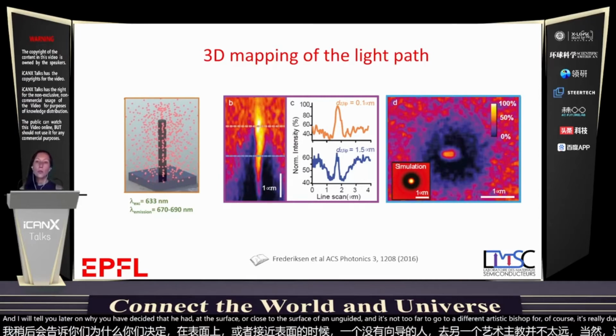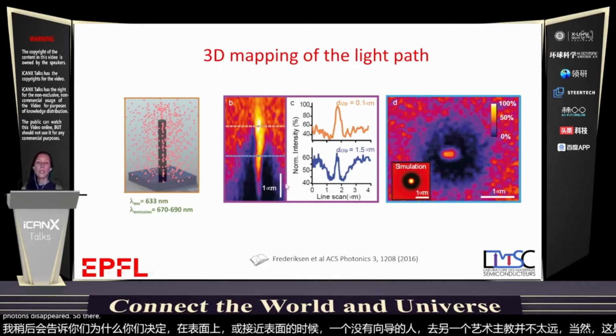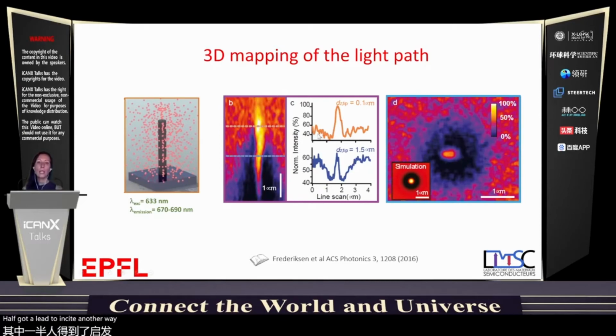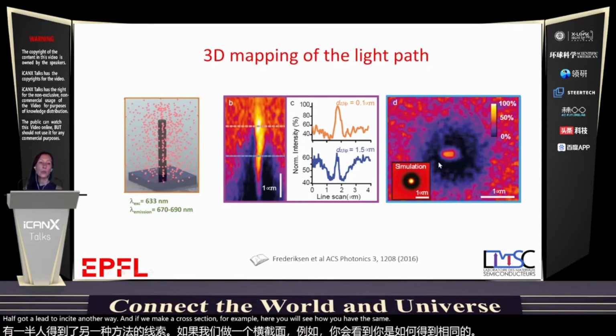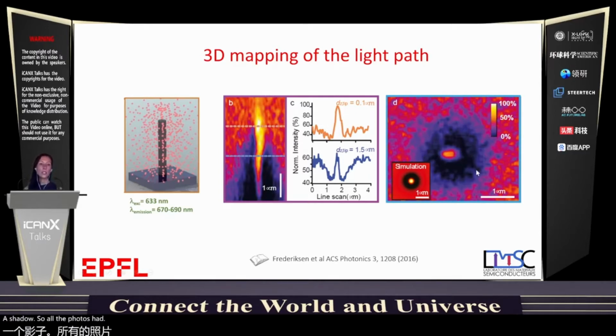And then when you go down, somehow the photons disappear. So there are still fluorophores there, but they don't luminesce because photons don't get there. All the photons have gotten inside the nanowire. And if we make a cross section, for example, here you will see how you have this high intensity close to the surface of the nanowire, and around you have developed a shadow. So all the photons have disappeared, they have gone into the nanowire.